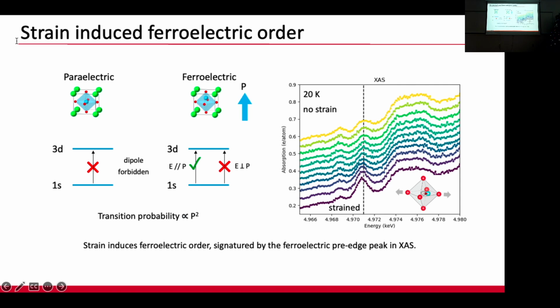How do we understand it? This feature actually corresponds to the 1s to 3d transitions in the titanium electron core levels. So in the paraelectric phase, the system is centrosymmetric, and for the 1s to 3d transition, the angular momentum change is 2, which is not possible. It's dipole forbidden by a single photon excitation.